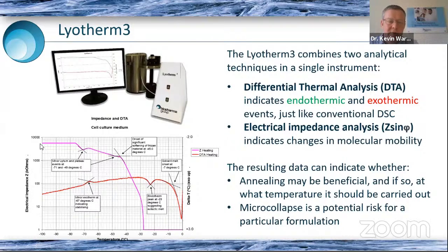And it can be quite difficult to understand everything that's happening that's relevant to freeze drying. But what this graph shows is the impedance, shown in pink, on the logarithmic scale on the left. And at low temperatures, the impedance is very high. As we warm the solution from -100, we can see various changes culminating in this rather large change starting at -45 degrees, where the impedance drops logarithmically from more than 1 mega ohm to virtually nothing.